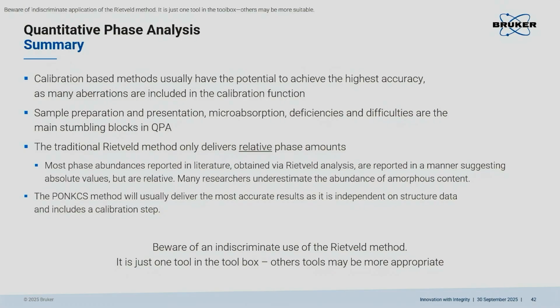Sample preparation and presentation, and microabsorption, are the most important stumbling blocks in quantitative phase analysis. Sample presentation and preparation is, I think, the worst. Preferred orientation can also lead to significant errors, but at least there's some hope to correct it. Microabsorption usually is not correctable. The traditional Rietveld method, this is what I said many times already, but I repeat it here because it's so important, because so many people are not aware of it, only delivers relative phase amounts. The PONKCS method will usually deliver the most accurate results, because it includes a calibration step.